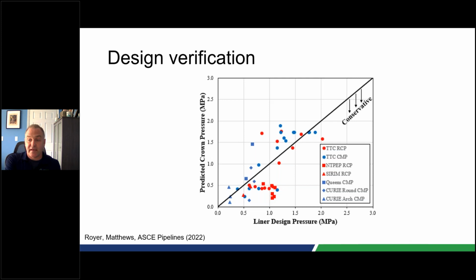What we did in this case is we tried to calculate what we called the liner design pressure, which was actually applied to a tested sample. Because we knew the thickness, the flexural strength, and the radius of curvature, we resolved those equations for pressure. What you will see here is the pressure that we measured versus what we predicted it should be. Anything that's below this line, a slope of 1, should be a conservative solution to the data point.